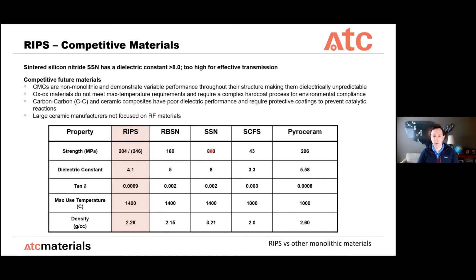And then compared to some of the other materials which may have previously existed on other missile systems, like a slip cast fused silica, the dielectric constant is similar, but the big difference is increased strength. So where the slip cast fused silica as a monolithic material has perhaps left a bad taste for some people because of prior poor performance, we think we found the right spot of strength and dielectric performance in monolithic materials. And certainly there are some competitive future materials of CMCs and carbon and different things like this, but they don't hit the same spot that RIPS does. And there's also some concerns about the composite materials and the variable performance if they're not made as homogeneous as they could be. So versus a monolithic material.